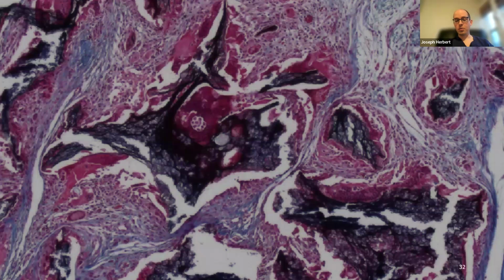This is what I think is a really beautiful picture for a number of reasons. For one thing, it looks like something you'd see in the Louvre, but on the other hand, it's very beautiful because it shows the black stuff is the hydrogel particles, and the blue is mature bone. If you were to zoom in a little bit closer, there's actually bone growing through the hydrogel, and the hydrogel itself is well integrated into this. The spacing and separation is just a post-processing artifact, but the hydrogel itself seems to be very agreeable for bone formation.